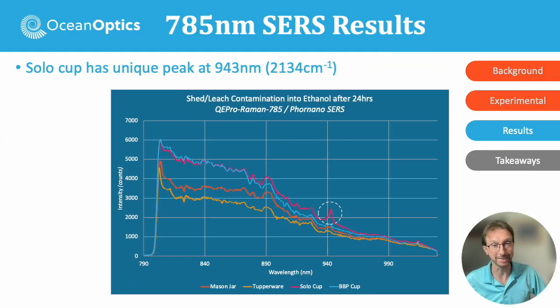Now, we also used a technique called SERS, which stands for Surface Enhanced Raman Spectroscopy, or Raman substrates, depending on who you're talking to. But this uses a nanostructure or nanoparticles to artificially enhance, that's where the E comes from in SERS, that Raman emission. So we're getting peaks that we can see that we wouldn't be able to see otherwise. It would be hidden in a normal bulk scan without the SERS effect. But most of them don't show anything. So none of these materials had any statistically significant activity except for the red Solo cup. So we get this peak right around 2134. So there's something going on there that's at least SERS active from the red Solo cup.